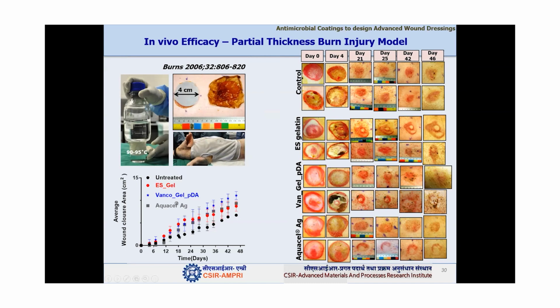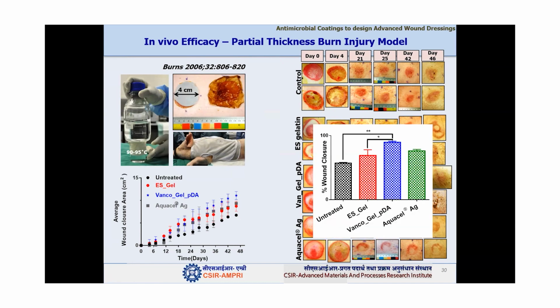And you can see here the wound closure for different kinds of dressings. You can see that for vancomycin electrospun dressings, the wound closure area is very, very good compared to the other dressings. And this is the plot showing the percentage wound closure for the control as well as the different kinds of dressings. And we got significant enhancement in the wound closure compared to untreated and the gelatin. The wound closure is very good, and it is actually comparable with the commercially available wound dressings.